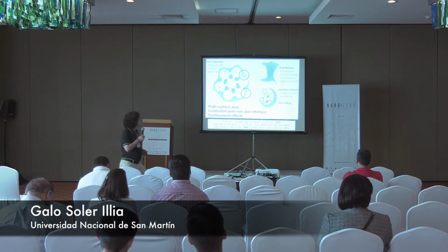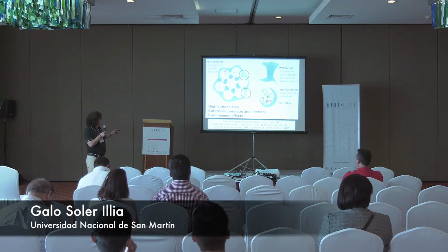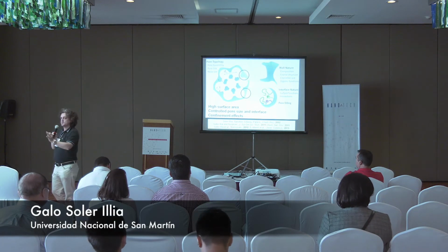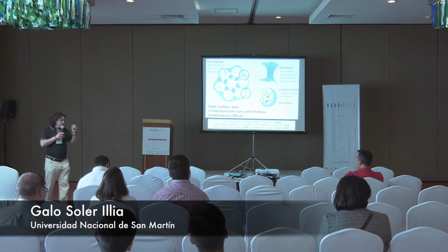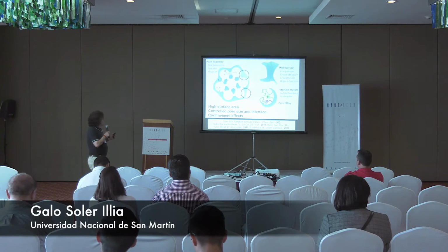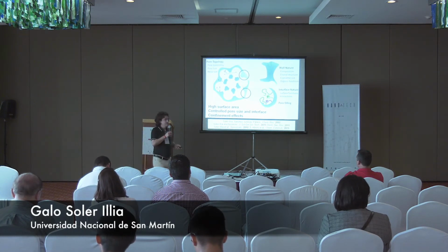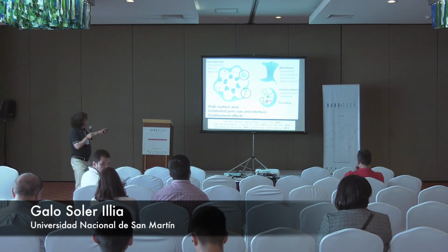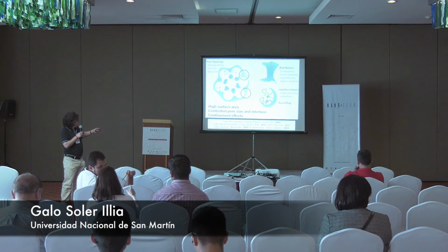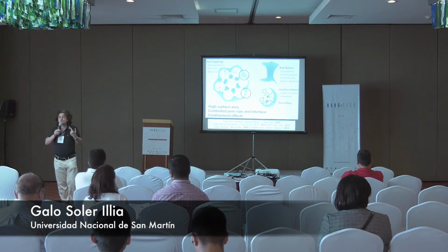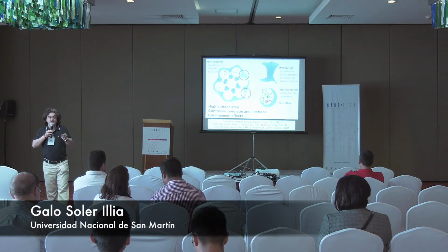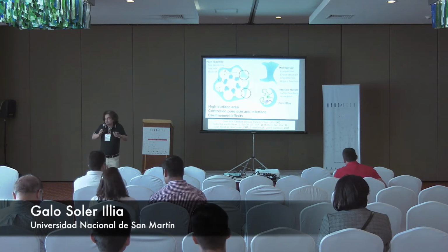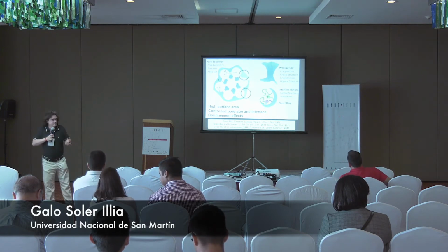Just let me tell you that in very few synthetic steps, one well-done precipitation, one calcination, that's it. One film deposition, treatment, and then thermal treatment to eliminate the surfactant. But you can create a very complex material in which you can tailor what happens at the walls. For example, if the walls are crystalline, if they are nanocrystalline, which is the crystallite size, which is the phase, which is the composition. Just one synthesis step. Of course, you have to know what to do.